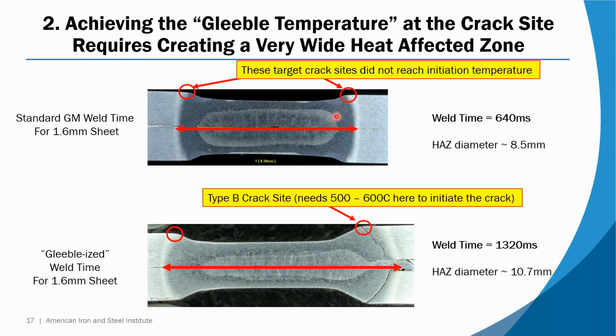All right, so how do we get this area up to the magic temperature where the Gleeble tester said there was going to be a crack? A standard GM weld schedule for 1.6 millimeter sheet is in the neighborhood of 640 milliseconds. And we created a heat affected zone diameter of 8.5 millimeters. Okay, so the red line.